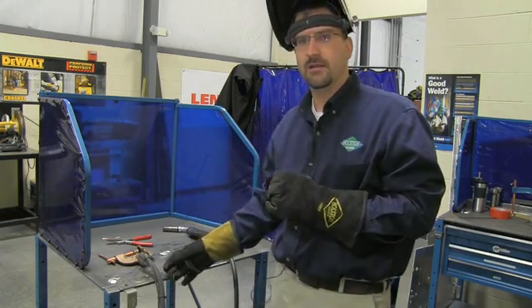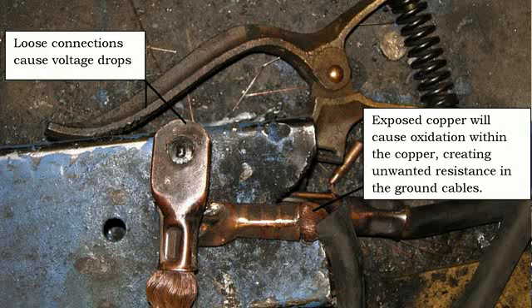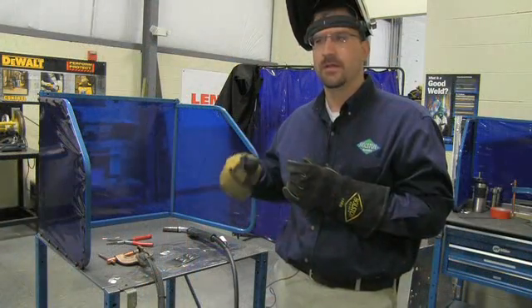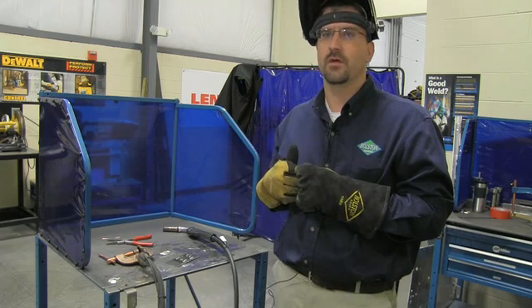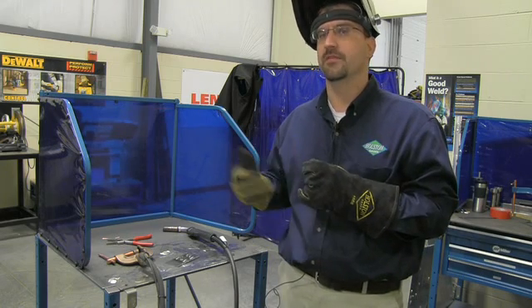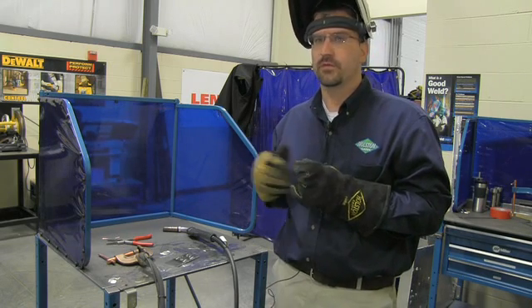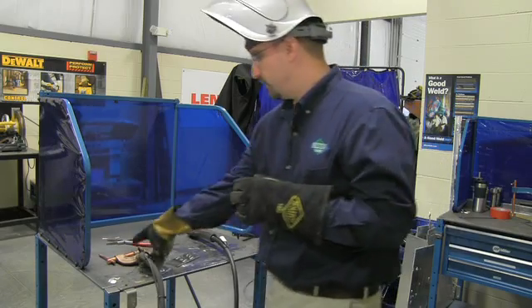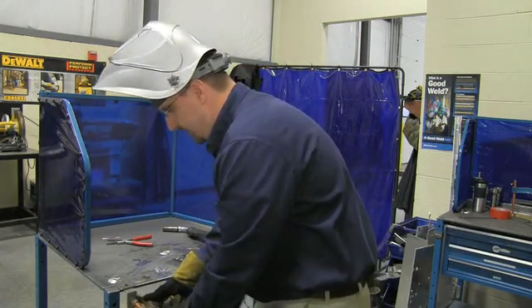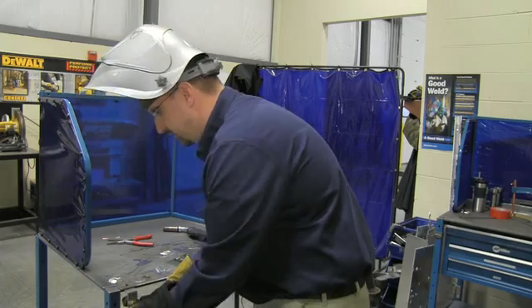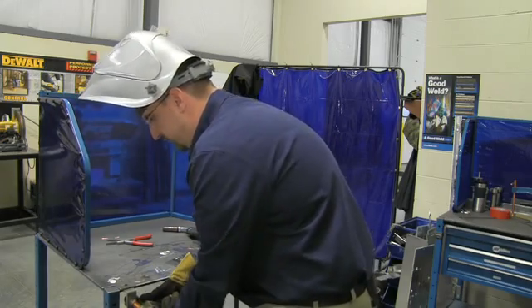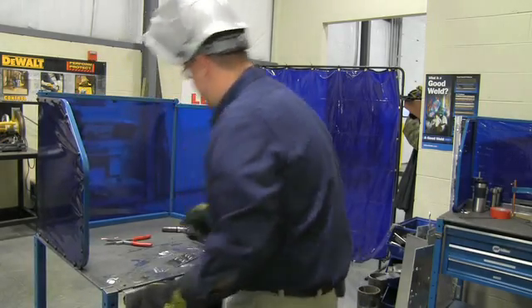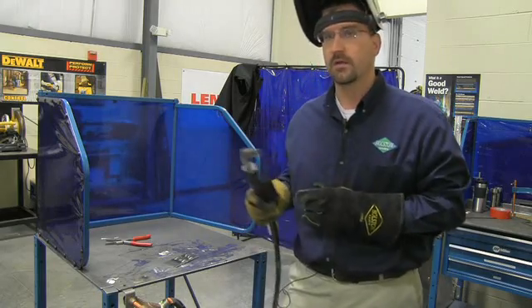Also, you'll see ground leads that are in terrible shape, kind of like what you see right here. These ground leads will, over time, the first arc start may not be bad, but after a few welds, they get really, really hot. And once that heat goes up, the resistance starts to go up, and that causes more voltage drops. So over the period of a day's time, the welding performance will start to deteriorate. So the best thing to do is to check your ground leads, make sure that they're sound and tight, and also make sure that the welder isn't trying to start with an excessive contact tip because he has improper consumables installed or worn consumables installed.